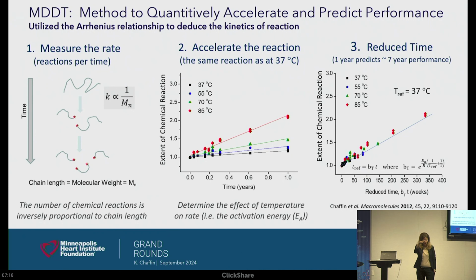You slow that reaction by cooling it down. We're doing the opposite, speeding up that reaction by heating, okay? And so what you have to be careful about is you make sure you don't turn on new reactions. You want to make sure when you heat that material up, the same reactions are happening that happen at 37. And we have ways to probe that chemistry to understand that.